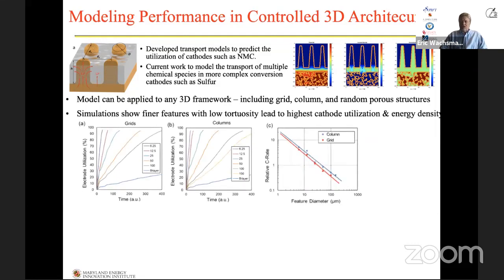They also give us some indication of what type of feature sizes we want to have. And so these are plots of the electrode utilization, how much of the lithium material in the electrode, which is filling the space between the columns, would be utilized as a function of time. The faster this goes, the more vertical that line would be, the more power we could get out of the cell. And there's for the grids and column structures, as you see here. And then the different colors there really depends upon what the feature size is in terms of microns. So, 150 microns is sort of the yellow, and the top one is about 6.25 microns. Clearly, the finer features give faster rate cycling capability.